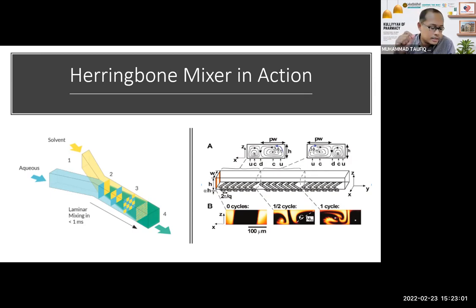So this mixing, this turbulent vortex, can be controlled using this herringbone mixer. This removes that uncertainty of the mixing. Therefore, you can see in the diagram on the left, one is no mixing, and then at 2 that is just laminar mixing only. But if you put in the herringbone mixer, now it starts to increase uniformly in how it mixes. Every checkered board doubles every cycle as they move down the channel. So at 3 there, you can see that it's more than 2, and progressively more and more mixed down the channel.